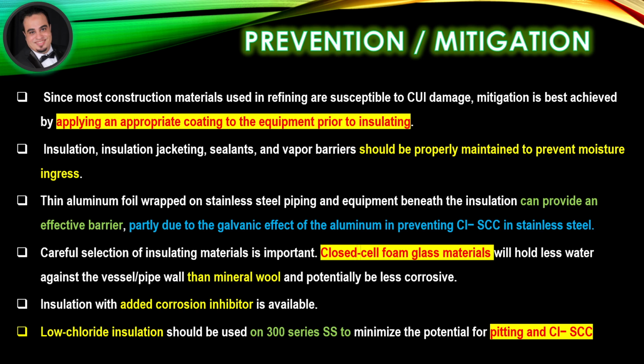Insulation with added corrosion inhibitor is available. Low chloride insulation should be used on 300 series stainless steel to minimize the potential for pitting and chloride stress corrosion cracking.